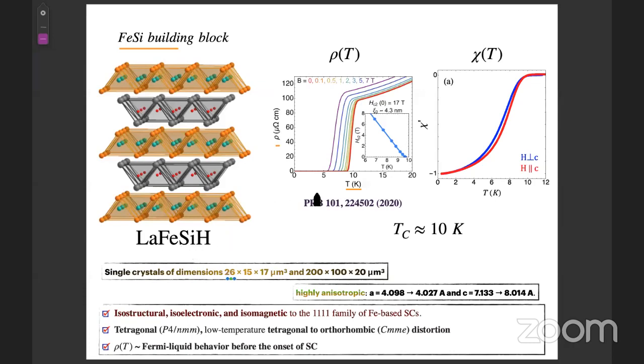Okay, but the interesting thing is that this sample is isostructural, isoelectronic, and isomagnetic, similar to the 1111 family of iron-based superconductors. We also studied the structure using X-ray synchrotron. At 15 Kelvin, there's a structural transition from tetragonal to orthorhombic phase. And the resistivity data in the metallic state follow normal Fermi liquid type behavior.